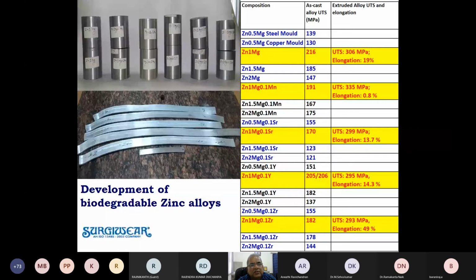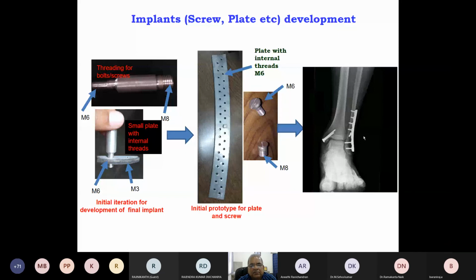Then along with the magnesium, we are also playing with the zinc, because zinc does not have the issue of the uncontrolled degradation. We have to increase its degradation rate. So we are working on the magnesium, zinc magnesium alloy with a low percentage of magnesium in it. And we have got some zinc 1% magnesium 0.1 yttrium with an optimum property which can be used for implant application.